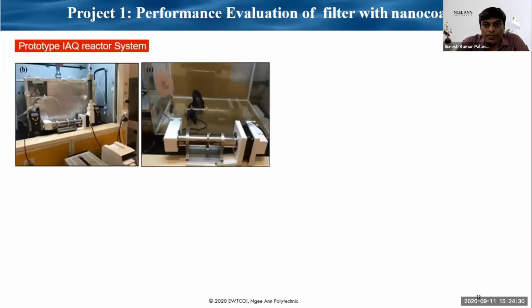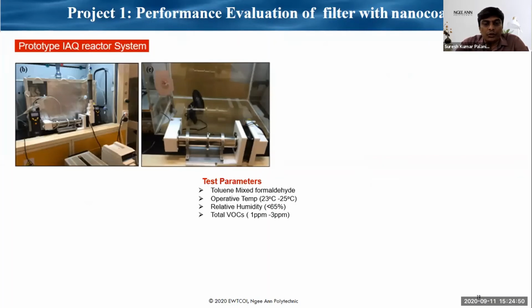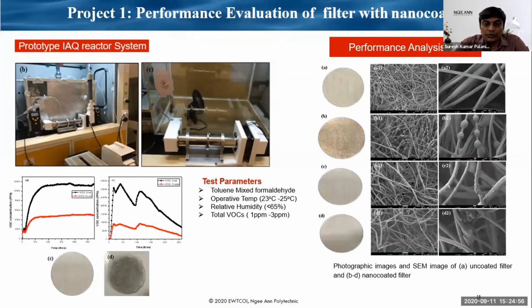In this project, the coating material was embedded with filters like carbon filters. We applied the nano coating onto those filters with different coating thicknesses. Then we did the performance evaluation of this coating on the filter for different VOCs like toluene and mixed formaldehyde, with an operating temperature between 23 to 25 degrees and a relative humidity less than 65. The performance shows these filters with the embedded nano coating have a good degradation of VOCs like formaldehyde and toluene. Now the company is taking this nano coating to filter end-user applications.